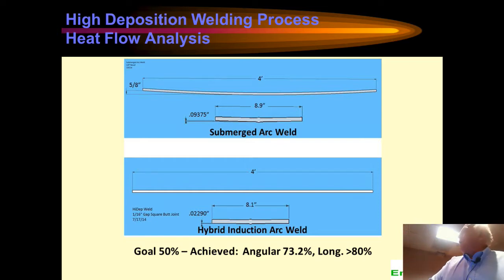In the bottom, over about an 8.1 inch section, we got 0.02 inches of deflection with the high deposition process, and we got almost 1/10 of an inch of deflection with the subarc process. So that was the benchmark they wanted us to compare to prove that we really were reducing the distortion.